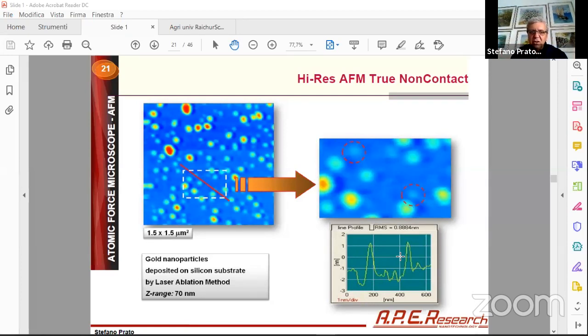Just because you have to think those nanoparticles on the surface have their own Brownian motion, okay? They vibrate on the surface, okay? And the smaller the size of the particle, the bigger the amplitude of vibration. So during the measurement, if you do not use a very good and sensitive instrument, if you touch one of these, like a ball, no? If you touch it, it will start to move. And they will start to coalesce into a much bigger dimension size.